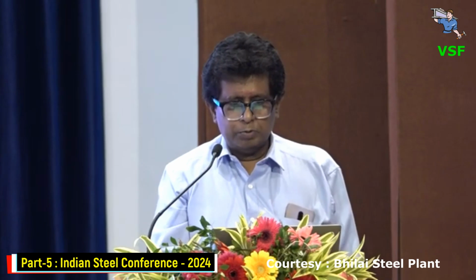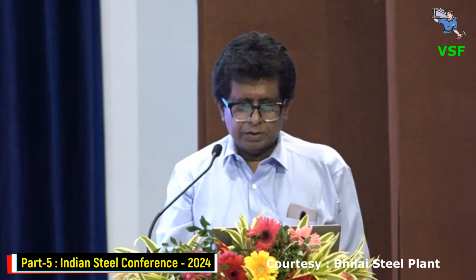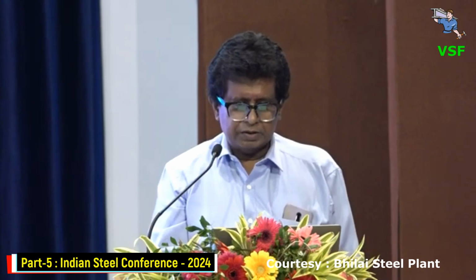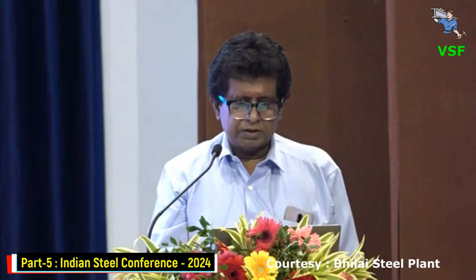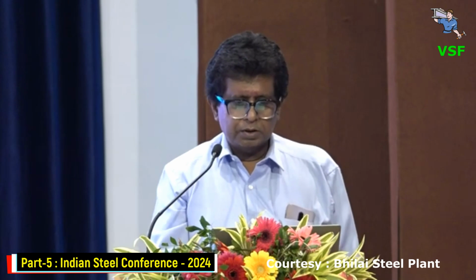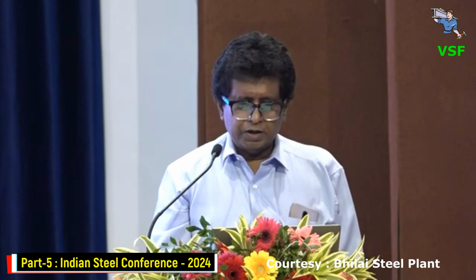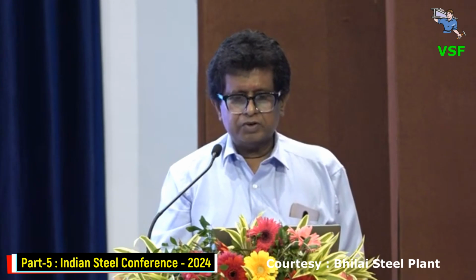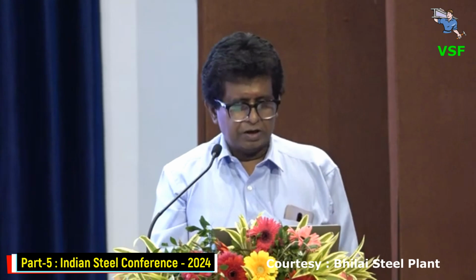And all these will probably lead to more refractory wear because of longer melt times, then EAF erosion of magnesia carbon bricks and carbon dissolution. And so we need to think or rethink about the refractory systems that go into these steel making parameters.